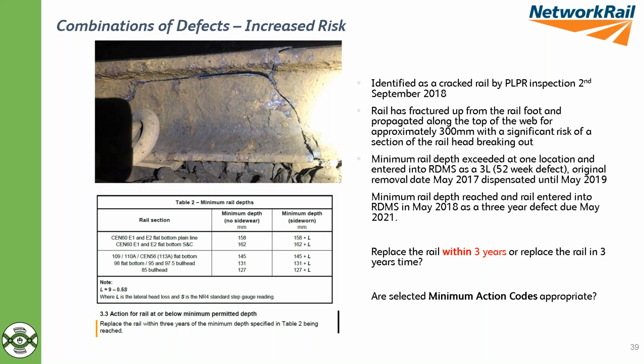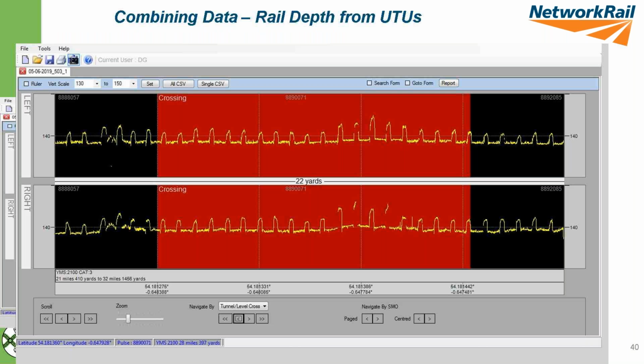One of the things we've tried to bring in now, this is an output of the rail depth data. So while part of the ultrasonic testing, we measure the signal from the top of the rail to the foot and back. By measuring the time that takes, we can effectively measure the distance or the height of the rail. Now, these two plots look a bit strange. These are actually crossings. So this is over a 22-yard length.